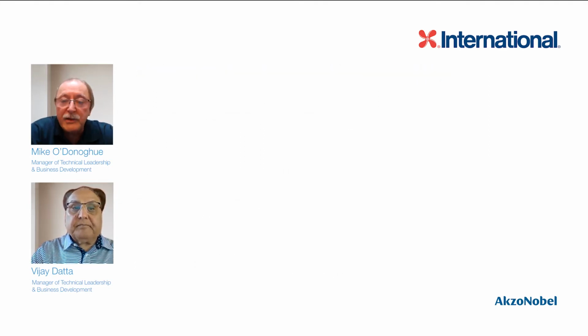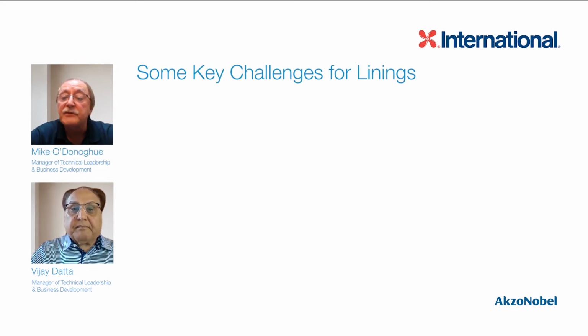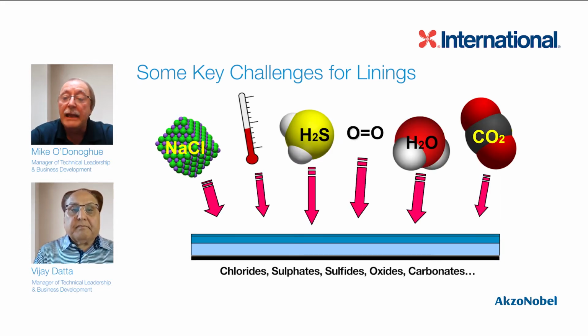If we're dealing with the oil patch, there are some very interesting key challenges that we have to face. We have very high temperatures, as you've mentioned. We have hydrogen sulfide gas and carbon dioxide gases. These are acid gases, and they ravage steel, and they certainly can cause all sorts of problems with coatings, so we have to deal with those. Obviously, there's oxygen, water, and we have salts as well, 100,000 parts per million salt in some of these vessels that we're dealing with, for example. And then the substrate itself, well, you have chlorides to contend with, sulfates, soluble salts, and you have insoluble materials like sulfides, which are cathodic to steel. So there are quite a few challenges that we have to deal with when we're dealing with these coatings.